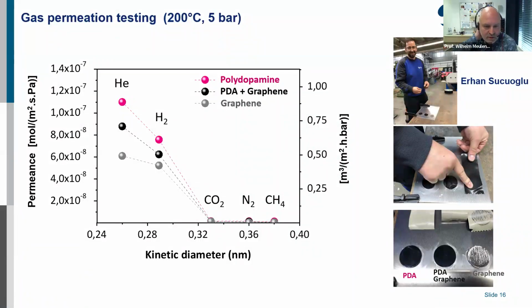And then we tested also again without any graphene, the converted polydopamine layer. And then we saw that it was much better than the graphene layer. So that means when we use a polydopamine membrane, we don't need any graphene layer on top. And then the question was how the attachment looks like to the support.